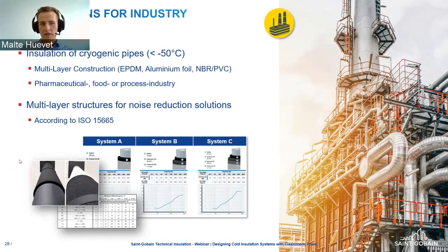Then we also have applications for the industry. A lot of our customers are using, for example, our elastomeric foam materials for very cold pipes, down to -80, -20 degrees, with a multi-layer construction. For the first layers, we always need the EPDM, then to protect the material while it's shrinking, against rubbing against each other, an aluminum foil covered layer. And then when we reach a temperature above -50 degrees, we can go to our normal material, the NBR PVC material. These are mainly customers out of the pharma or food industry.